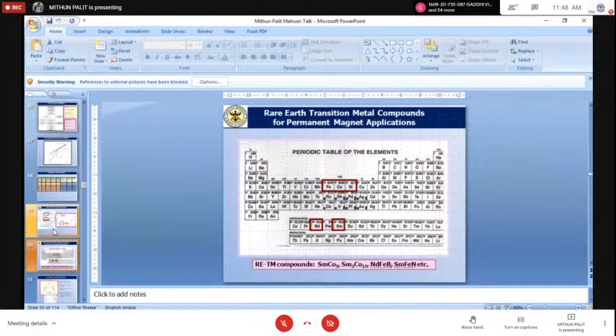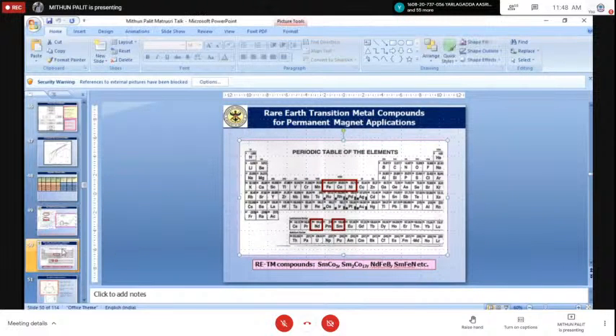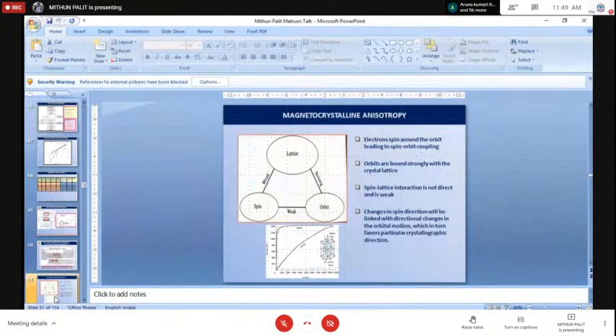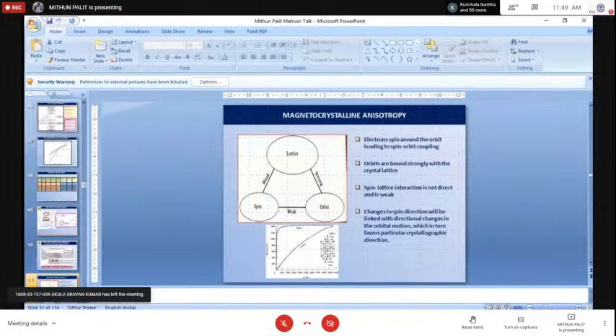Well, most of the rare earth permanent magnets. The rare earths are the lanthanide series, which you can see at the bottom, with the 14 element series in the periodic table, starting from cerium and ending at lutetium. Of these 14 elements, normally the first 7 are opted for preparing rare earth permanent magnets, in combination with transition metals such as iron, cobalt, and nickel. But what is the specialty of this rare earth? These rare earth materials have their magnetism stemming from the 4f orbital, and the 4f orbital is not delocalized. That means the electrons of the 4f orbital are not delocalized into the crystal field, or they are not going into the other crystal field.